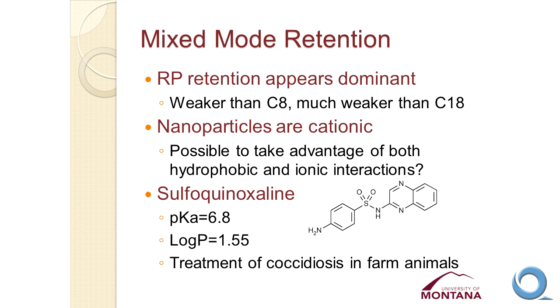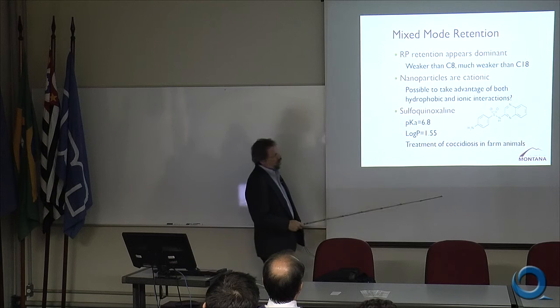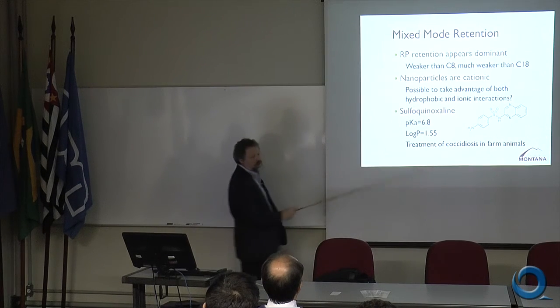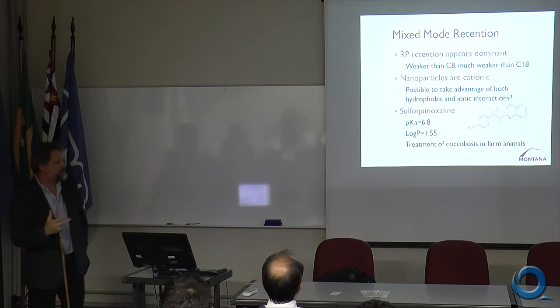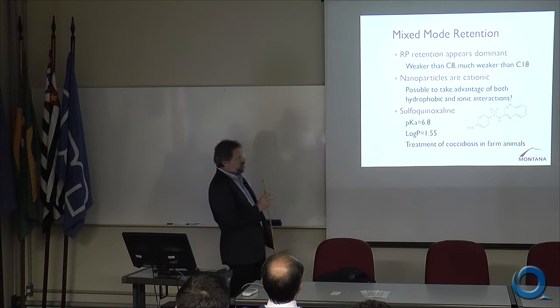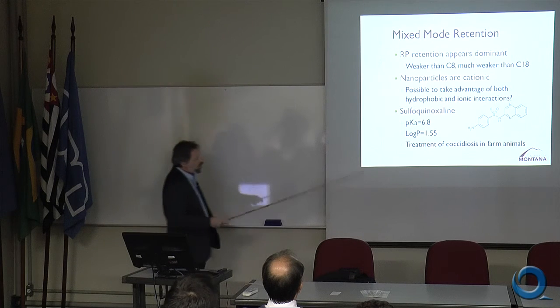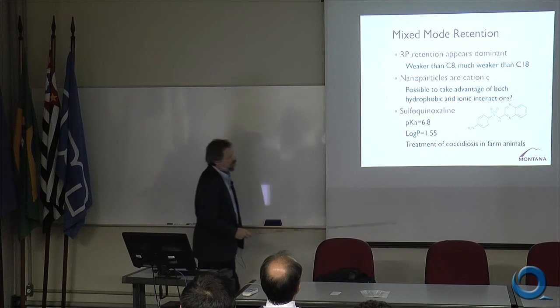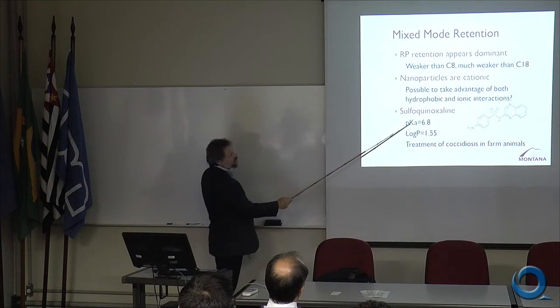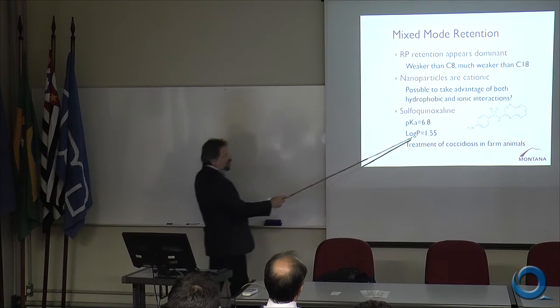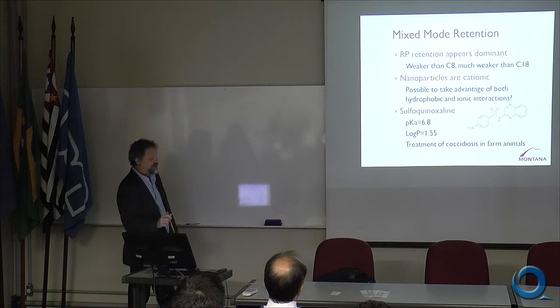So the next question was, is there some other feature of these nanoparticles which would give them an advantage for the extraction of particular types of compounds? And so we started to look at, could we use a mixed mode retention mechanism? The nanoparticles are cationic, and they're also hydrophobic, we know that. So if we could extract a molecule which is anionic, we might expect to see strong ionic interactions as well as the hydrophobic interactions to retain the molecule on the surface and also to give us a high degree of selectivity. We looked at sulfoquinoxaline as an example. This is a compound which is anionic at higher pHs and neutral at lower pH. It has an octanol water partition coefficient in the neutral form of 1.55, so not terribly hydrophobic.